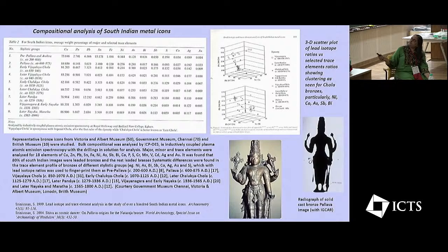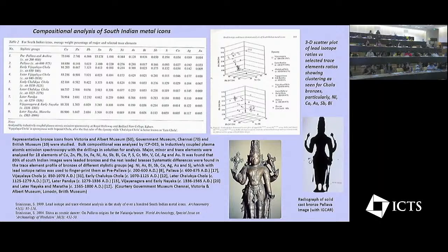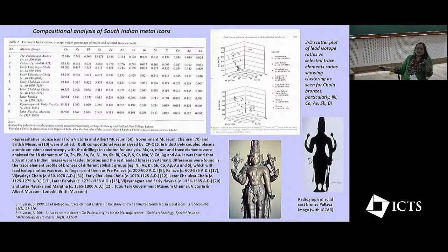And what I actually found is that some of the chalcophilic elements here, nickel and cobalt particularly, tend to reflect the ore source. Nickel, cobalt, arsenic, antimony, and bismuth. These are what we call the chalcophilic elements. I mean, iron is not a very typical element because iron can vary very randomly, because iron can also come in from some iron ore, because sometimes you get chalcopyrites, you get associated iron ores, and it can come from flux, it can come from a range of sources. So iron is not what we call chalcophilic, but these other elements are. And gold and silver are also chalcophilic.